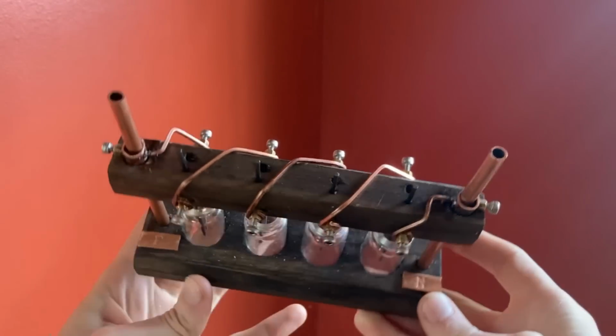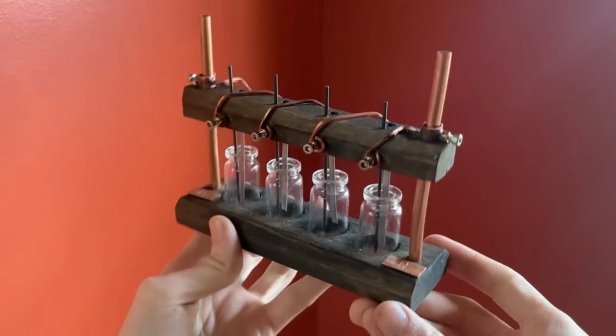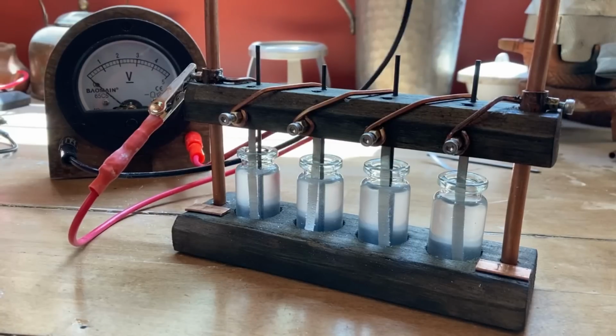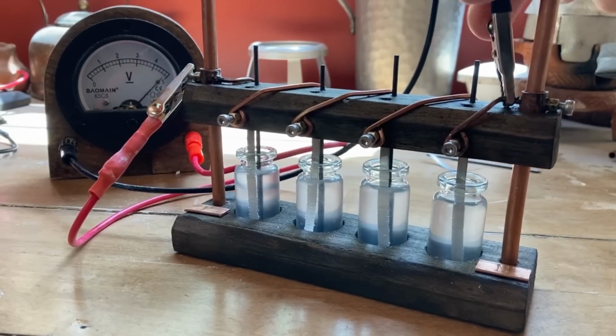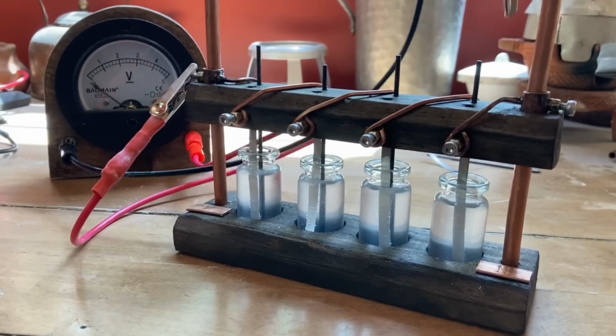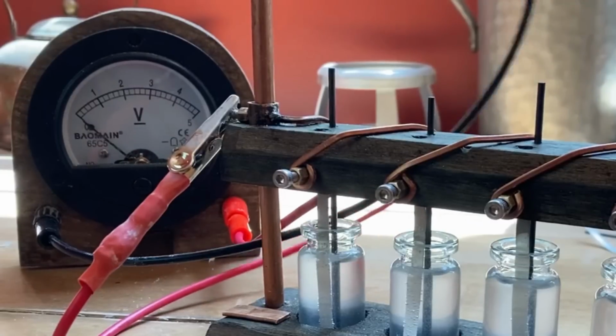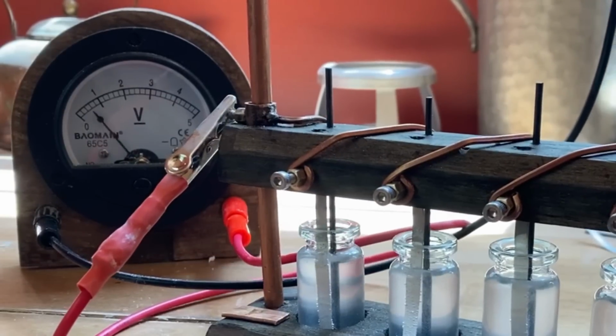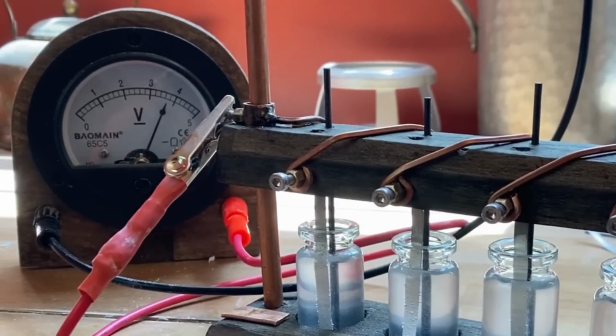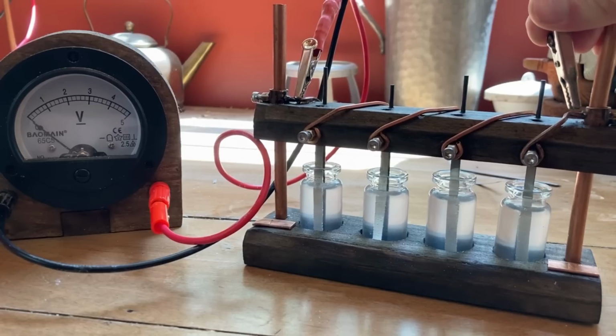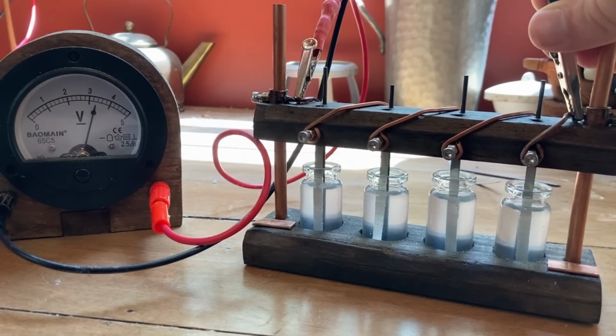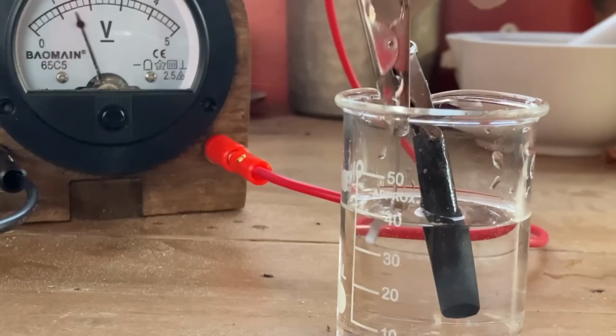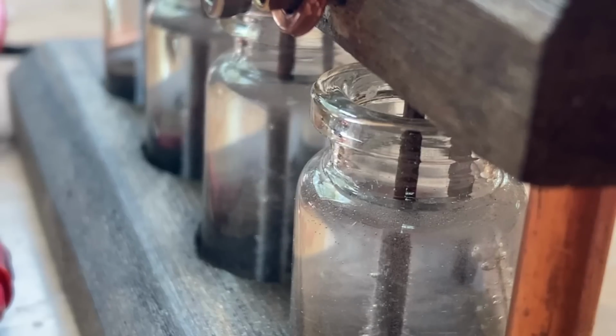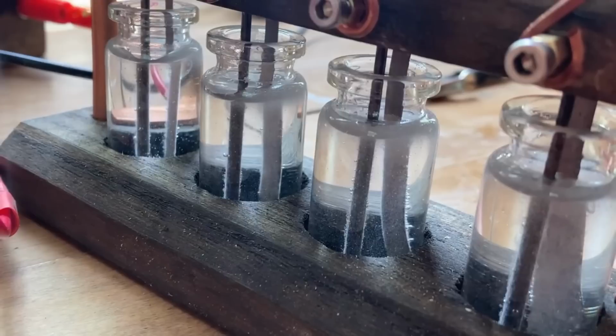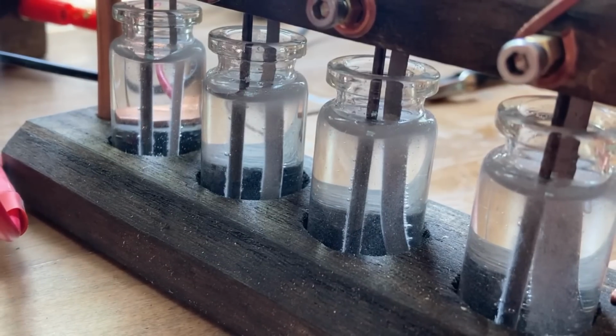With the finishing touches added, my battery is complete. Let's connect it to the voltmeter to see if it works. A much higher voltage is being produced, as the electrical potential of each cell is added to the last. Despite the fact that this is still just magnesium and salt water, by combining multiple cells, it's producing a higher voltage, higher even than we were able to achieve using corrosive acid. By shorting the battery and connecting one end to the other, we can see a copious amount of frothing.